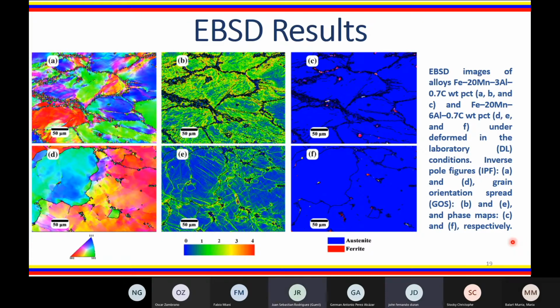Sebastian? Okay, continuing with EBSD results. By this technique, the results obtained in the processing by hot forging were characterized, which was at approximately 950 degrees Celsius. Here are the one-step deformation results. According to the graph, for both compositions, the recrystallization phenomenon is the same. It is continuous dynamic recrystallization in a necklace structure.